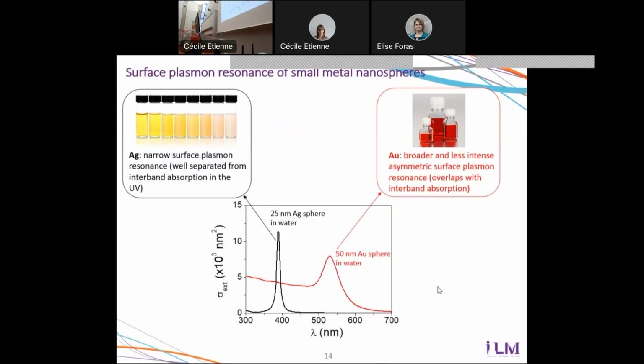So more precisely, you have here some examples of the extinction spectra of silver and gold nanospheres in water. For silver nanospheres, you have a very sharp, narrow, and symmetric resonance here, which occurs at the border of the ultraviolet and visible range near 400 nanometer. And for gold, you also have a resonance, but it's not at the same wavelength. It's near 550 nanometer. And also the resonance looks quite different because it's much broader and it's not symmetric because it overlaps with the background of bulk gold absorption.